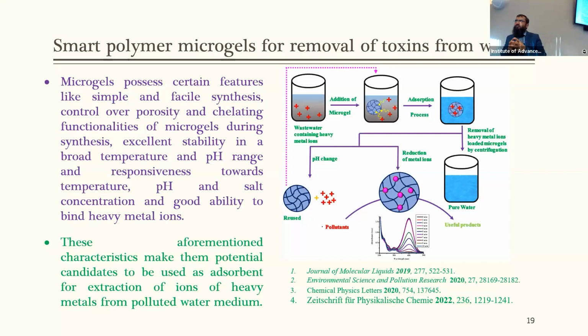The smart polymer microgel system can also be used as an adsorbent to remove highly toxic chemicals from aqueous medium. The methodology or approach is simple. We simply add the microgel system into the wastewater containing heavy metal ions. The metal ions present in the water go into the polymeric network due to electrostatic attraction between the negatively charged microgel particles and positively charged metal ions. Then these metal ions are adsorbed into the polymeric network. We can simply remove the metal ion containing polymer microgel by simple centrifugation, and we can get pure water, and we can easily remove the heavy metals from aqueous medium using microgel as an adsorbent.